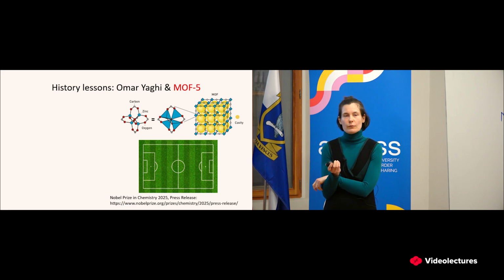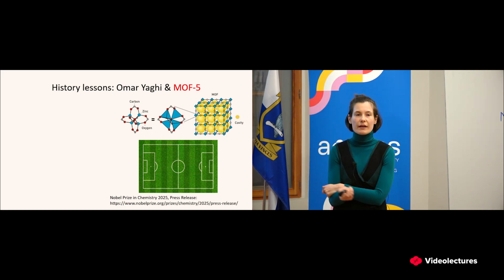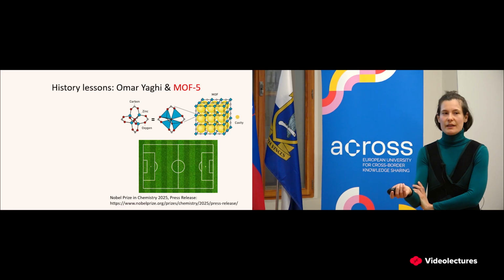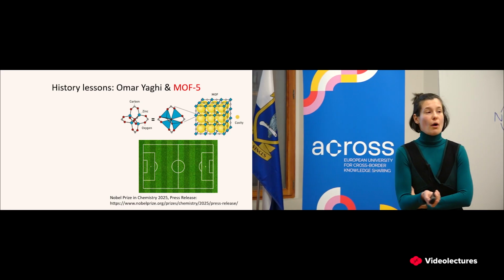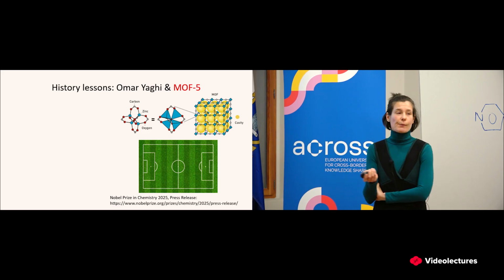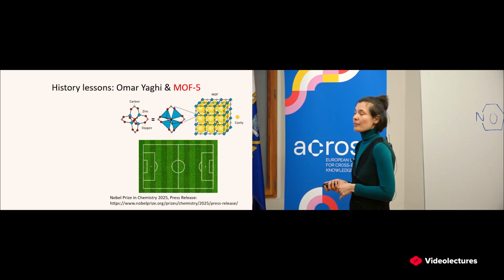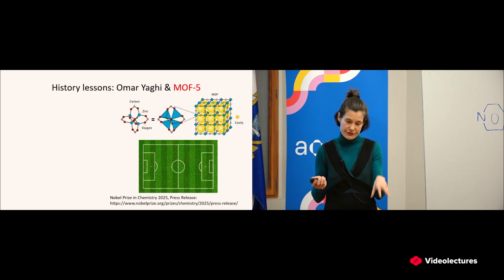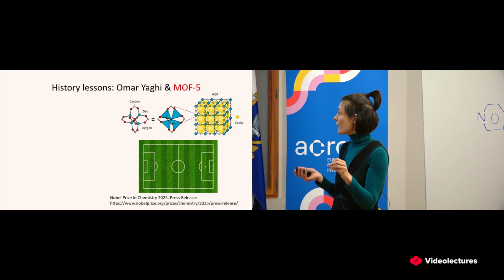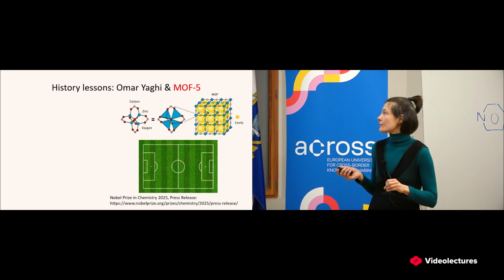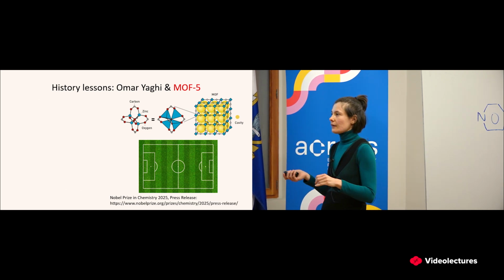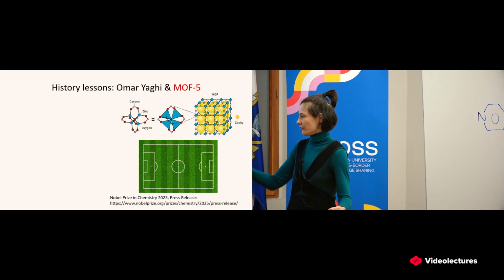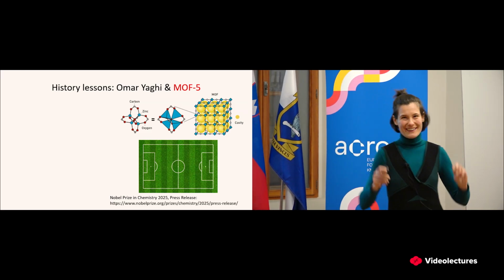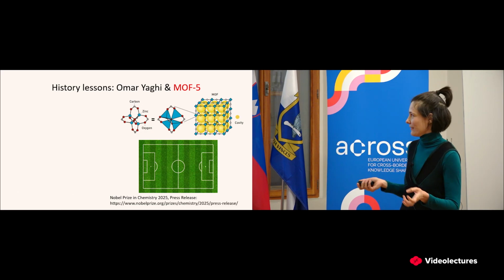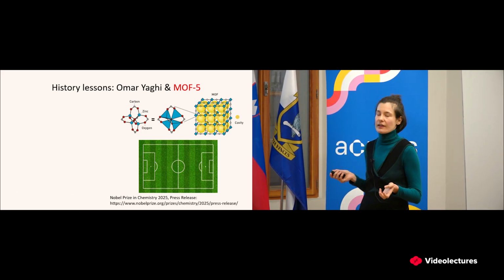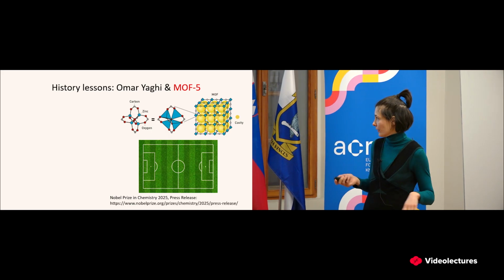Okay, so in one of the early slides, I have written that Professor Yaghi's major contribution, and also the reason why he was part of this Nobel Prize, was the so-called MOF-5. So here there is some context to that. Here, MOFs are becoming more complex, as you can see. Instead of having just a metal ion, we actually have a metal cluster, which is formed in situ. The way this is synthesized is you take a metal salt and an organic linker, and while this is cooking, the cluster is formed and the MOF crystallizes. It is not really feasible to synthesize these clusters on their own and then form metal organic frameworks.